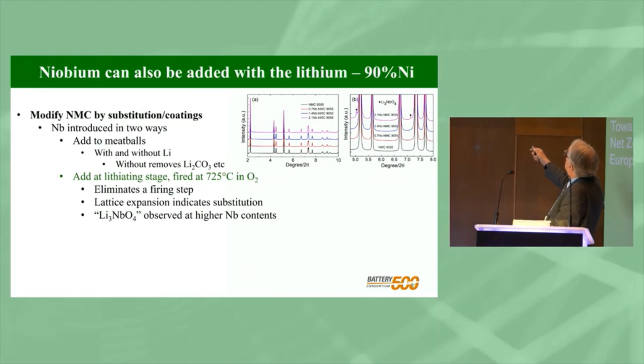And we got essentially perfect material all the way from 0 to 2%. At the highest niobium contents, you can see we're now getting some surface species of this complex niobium oxide, but at lower niobium contents, we don't see that. So in this case, the niobium's now gone totally within the lattice, so we've now got a substituting material, and this is the extra phase we see. We see this lattice is expanding a little bit, which proves that the niobium is in fact going in there.